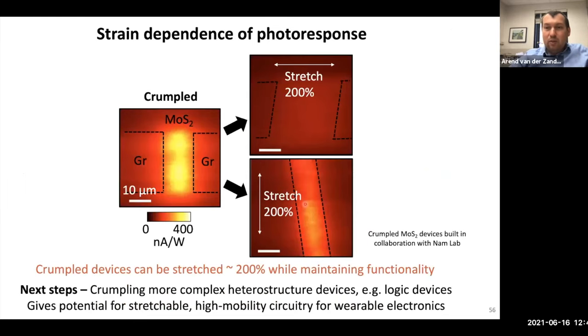So here, what we're seeing, we use a special technique called scanning photocurrent microscopy. We can measure where the photosensitive region of the device is. So on the left, in this map, we're seeing that the photosensitive region is in this MoS2 between the graphene electrodes.